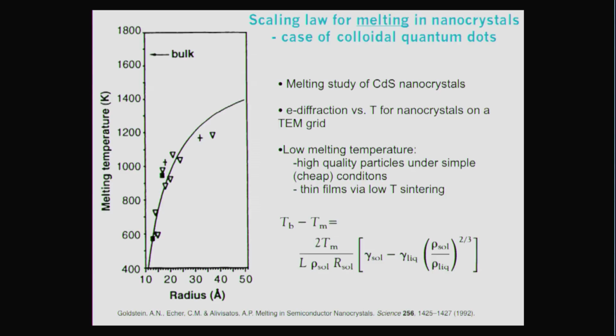And so that's an easy observation to make in the early days, but it's quite interesting in itself immediately, because it means that you can take materials which ordinarily would be formed at high temperatures, but when they're nanoparticles, they become accessible to processing at temperatures hundreds of degrees below where the normal material would be processed. And that turns out to have a lot of significance.